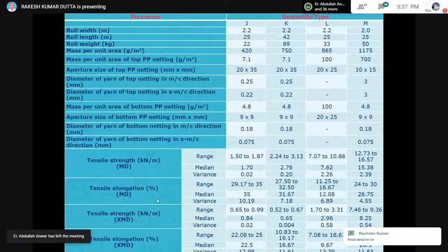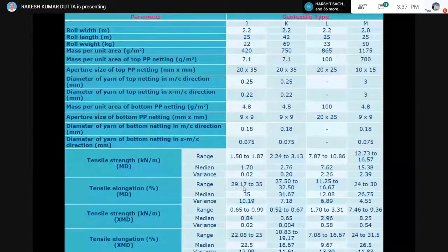And the same thing is the tensile elongation. If you take a loose web and apply a tensile load, the strain is going to be almost zero because the web is going to come out. But because of stitching provided on both faces or on a single face by the use of natural yarn or PP yarns, these materials show some strain, and the median value of the strain varies: 35% for the first material, 31 for the second, 12 for the third, and 26.75 for the last material. So for the last material we are getting a larger strain in comparison to this one.